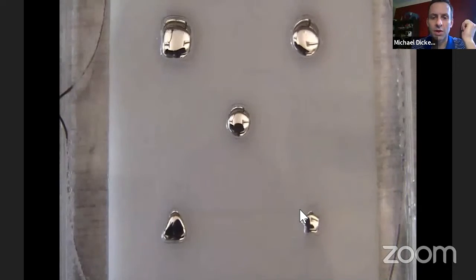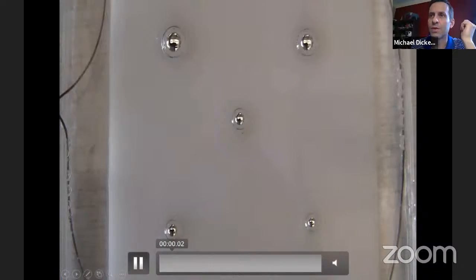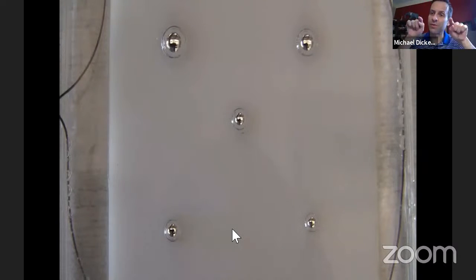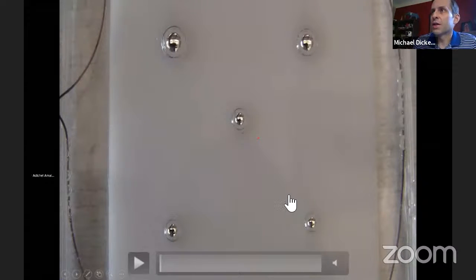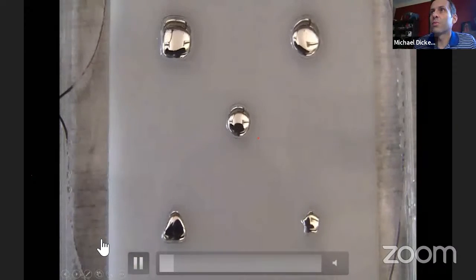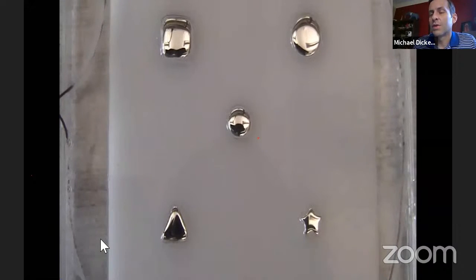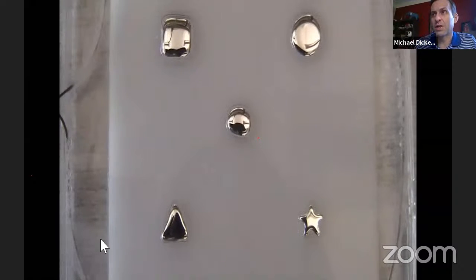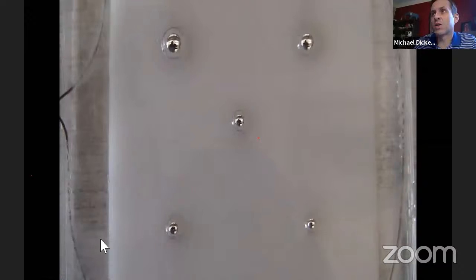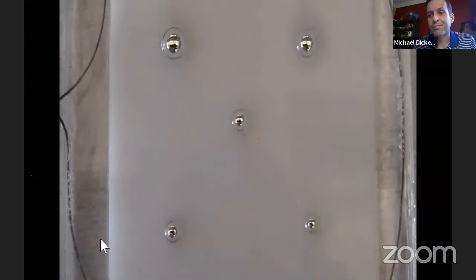So this video, you're looking from the top down. Let me start it over again. So what we have here is 5 liquid metal droplets, and they're sitting in a mold. So you're looking top down. So gravity's pushing into the screen, and initially it is at high surface tension. So it's a sphere, and if you apply a voltage, which you can do because there's electrodes underneath it, it will squish down into the mold. And then when you switch the voltage off, it beads back up.